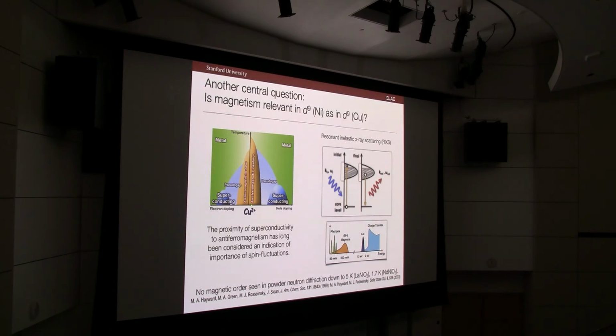Now, this notion of having proximate magnetism is so important for superconductivity, not just in the cuprates, but in heavy fermion and other systems. We're very curious to know what might be going on for the nickelates. The problem, as I told you, is we can only be stable up to like 150 angstroms. So this is miserably impossible to do by things like inelastic neutron scattering. But we've been very fortunate to collaborate with people and developments in the field of resonant inelastic X-ray scattering. It's a photon in and out technique; by tuning to core resonances, you can pick up the magnetic excitation spectrum, despite being so thin.